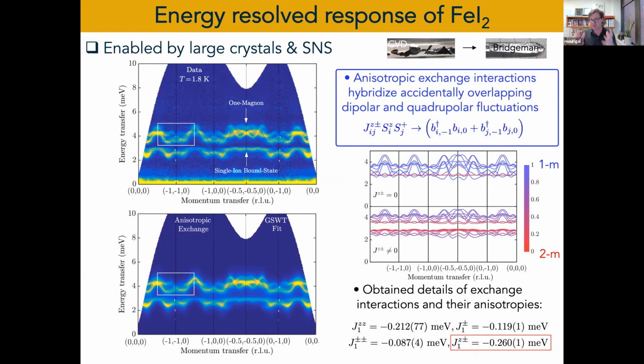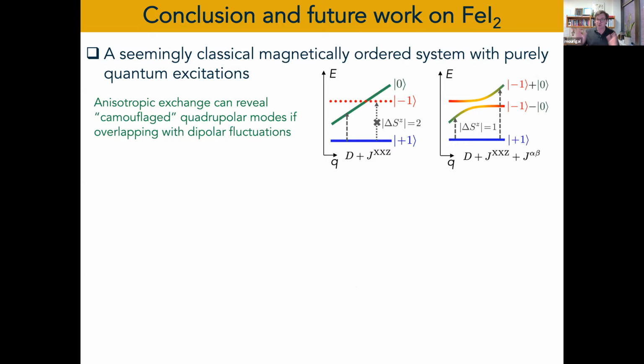And so, long story short, here we can fit, and the students did amazing work to understand this, and we realized, in fact, in the system, the off-diagonal interaction in this parameterization is the largest interaction in the system. It's not big, but it's a dominant interaction in the system. Okay, so that's essentially the message here that I want to convey about this material.